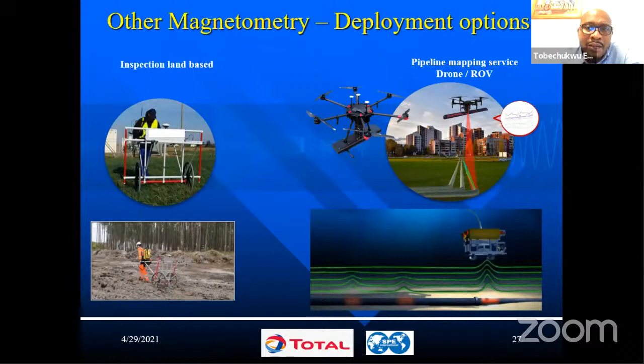There are developments to put them on drones, so that if the line is on the surface, which is not common in our environment, as most of our pipelines are buried, it can run over the lines, or on an ROV. But this also has its own challenges, especially if you are subsea and your visibility is not good enough to know where the pipeline is. However, even though the line is buried to about 1 or 1.5 meters, you will still pick up this signal, because onshore you are able to pick it up when the pipe is buried.